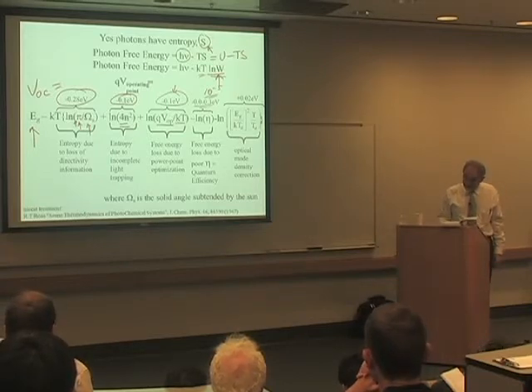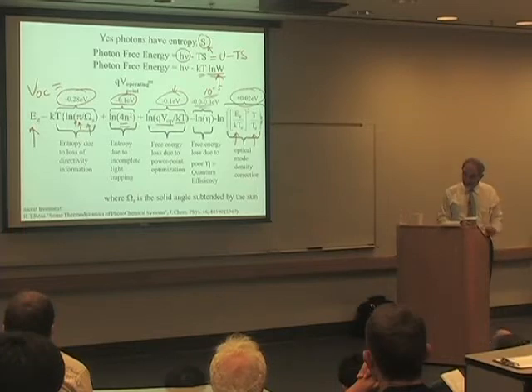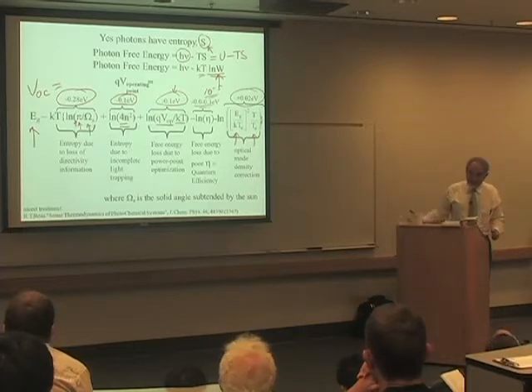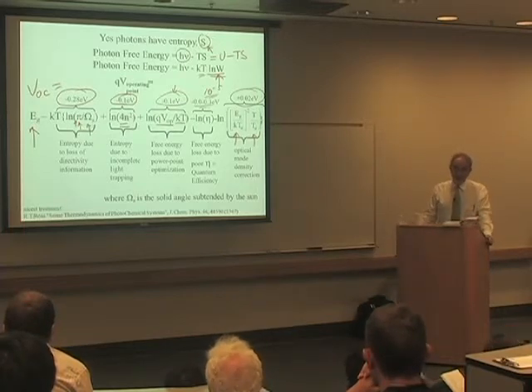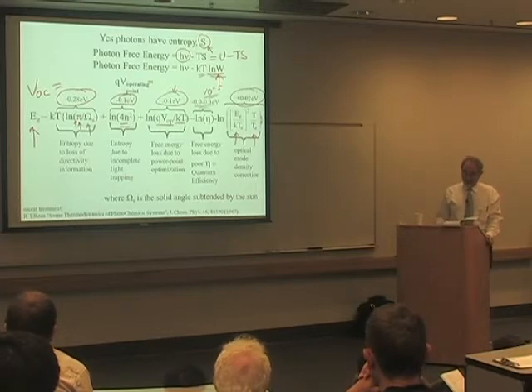And then here's another term. This is a correction for the optical mode density. This term is of order magnitude unity. It's only a 20 millivolt term. But now I've broken down the voltage of a solar cell. You start at the band gap, and you give up a lot of entropy terms.